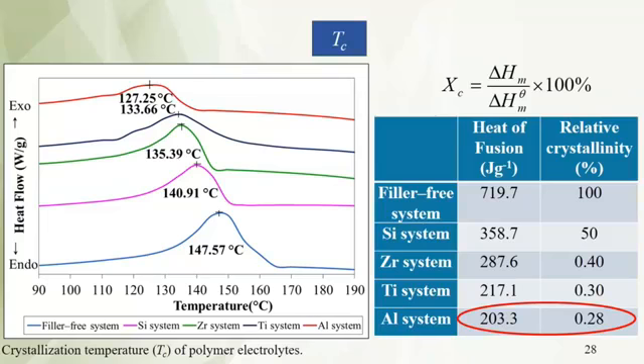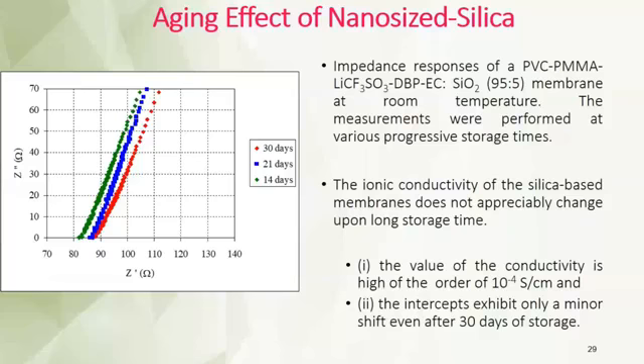And this result shows that incorporation of nanoparticles can reduce the crystallinity, and we can observe the relative crystallinity and also the heat of fusion of the nanoparticle-based materials are lower. And generally, amorphous natures are preferred for high ionic conduction. And on top of that, nanoparticles can retain the high ionic conductivity for prolonged times. So this is what we call the aging effect of the nanoparticles in polymer electrolytes.